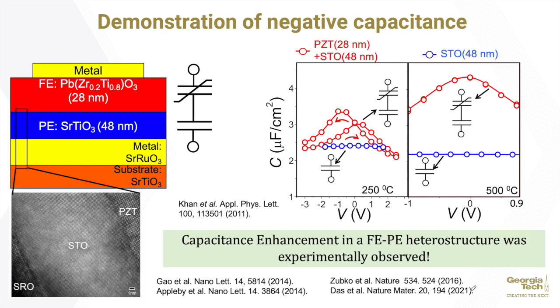Now, we started working on this concept of negative capacitance and to demonstrate it experimentally. In our very first experiment, we took the prototypical ferroelectric lead zirconate titanate, and as a paraelectric material we took strontium titanate and made a heterostructure out of it. And then we measured the capacitance. So here, this is the most important result from our first experiment. We took 28 nanometers of PZT and as the paraelectric material 48 nanometers of strontium titanate.